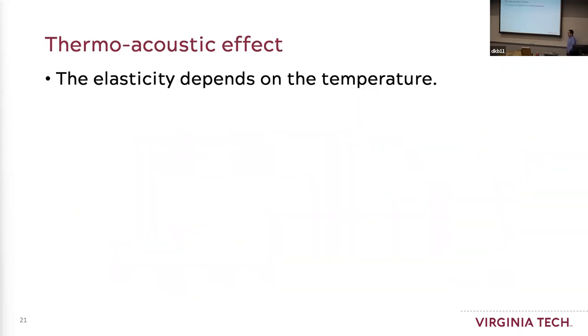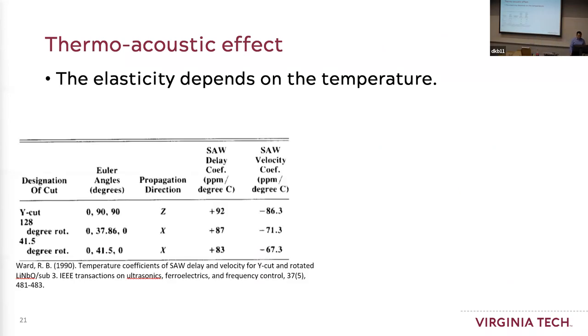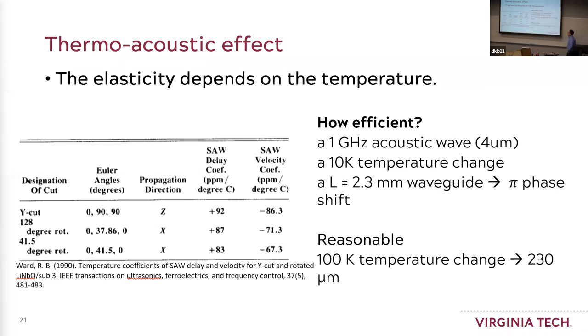And now we talk about another way to control this acoustic wave on chip, which is using the thermal effect. The thermal acoustic effect is actually utilized. You can imagine when you heat up a material, the elasticity or the Young's modulus of the material will change accordingly. So for lithium niobate, this can be a very efficient way to control the acoustic wave. This is how the phase velocity changes versus temperature. It's almost 100 ppm, parts per million, per degree.